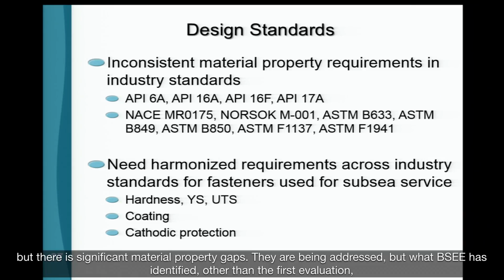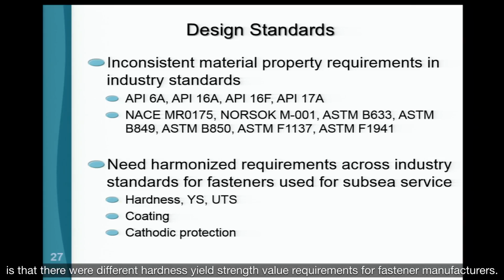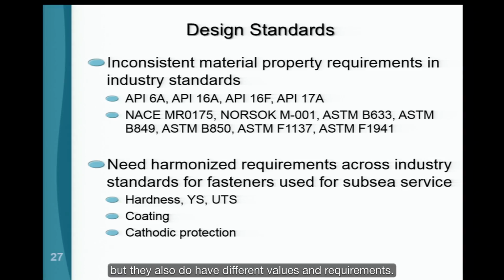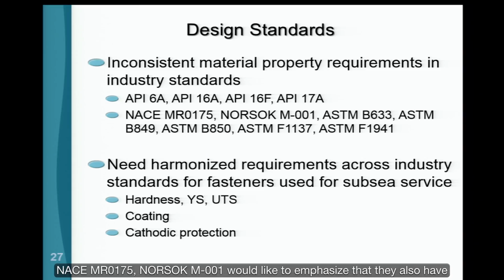They are being addressed, but what BSEE has identified out of the first evaluation is that there were different hardness and yield strength value requirements for fastener manufacturers. The other industry standards, realize that NACE is a very in-depth corrosion standard, but they also have different values and requirements. NACE MR0175, NORSOK M-001; I would like to emphasize that they also have different requirements for fasteners that are used with cathodic protection.